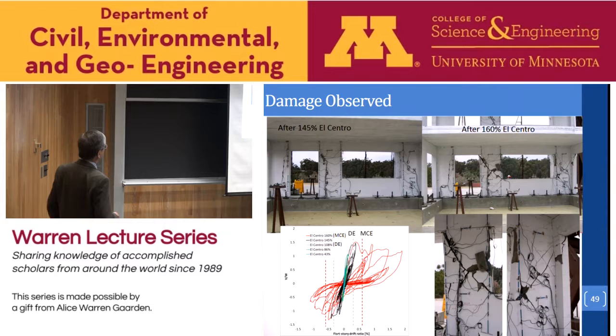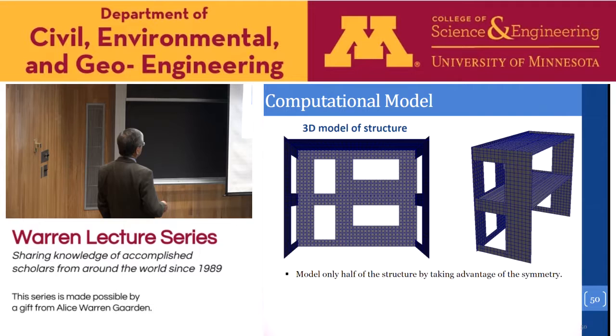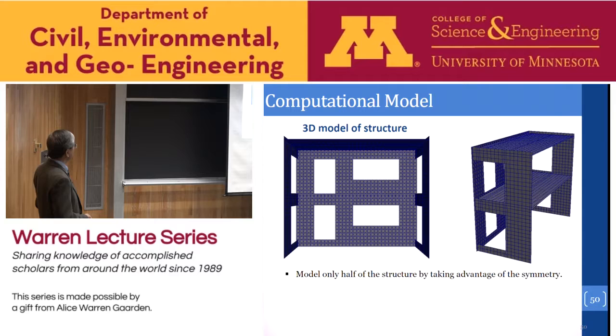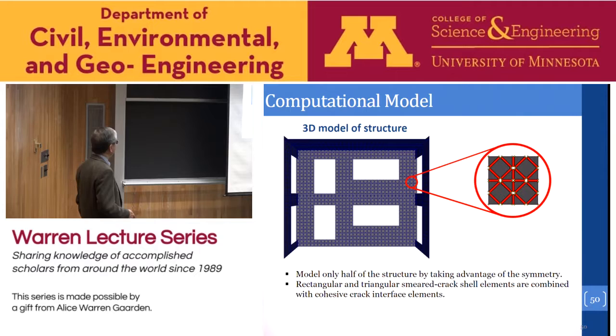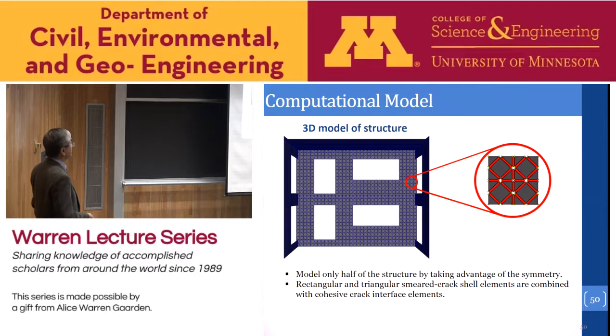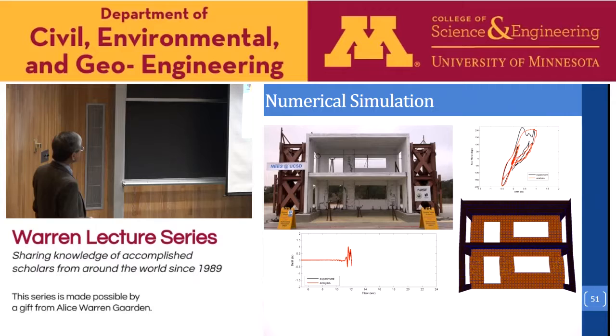So we did some finite element modeling. We took advantage of symmetry because it was subject to uniaxial motion, so we just modeled half of the structure, and this shows the discretization of the structure. We use rectangular and triangular smeared crack shell elements combined with cohesive interface elements like we developed for unreinforced masonry, and we also modeled the reinforcement. So this shows the comparison of the model with the test.